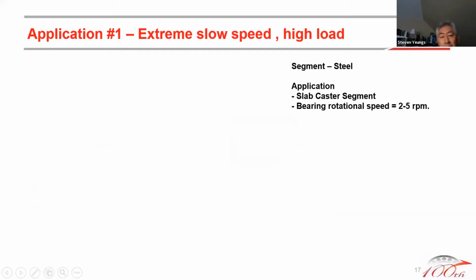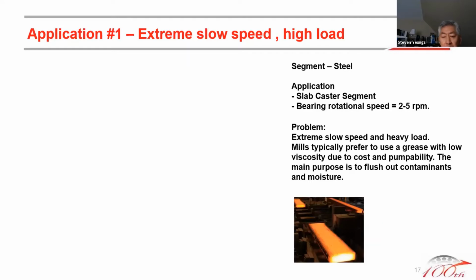This is, and I worked many years in the steel industry, involved in that area. One of the very typical applications is the slab caster, where they produce the steel slab. Bearing rotational speed is 2 to 5 RPM. That's very typical. The problem is extreme slow speed and heavy load. The mill likes to use just a grease with low viscosity due to cost and pumpability. The main purpose of using the lubricant is to flush out contaminants and moisture. So because of that situation, what can you really do?